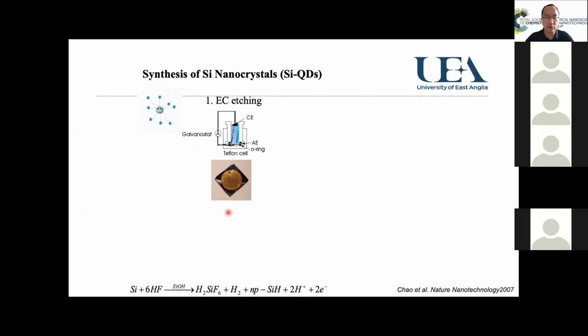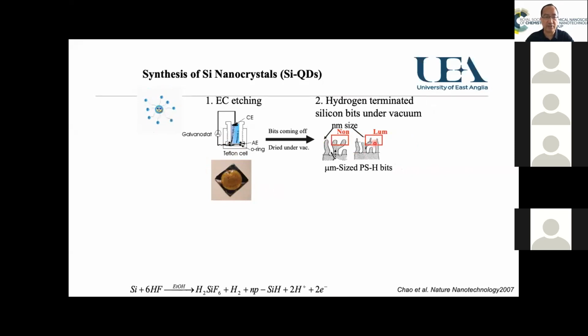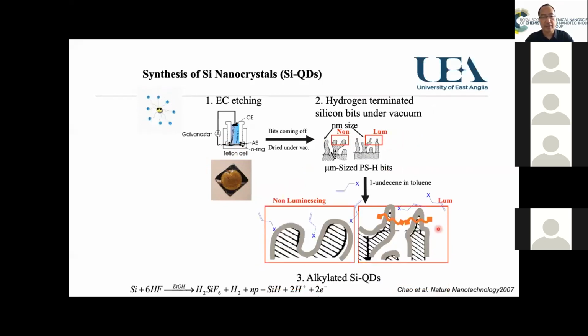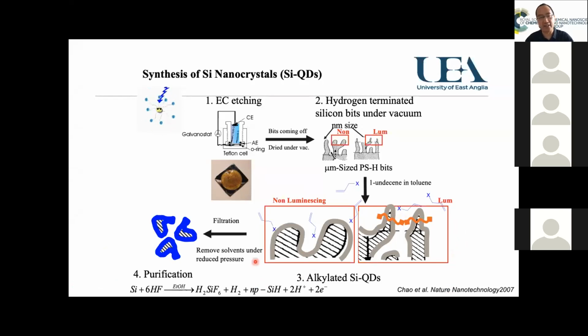Basically at that time, we were using the top-down method. What we did is cut a silicon wafer into silicon chips and put them in electrochemical etching, and then we get a porous surface. On the surface, some sizes are still big, and somewhere we get small-size silicon. If we put that in some reactions, say in alkene solutions, we can grab these bits off, and then with some purification and filtration, we get these small-size silicon particles.